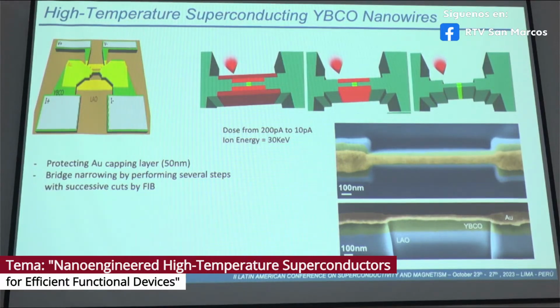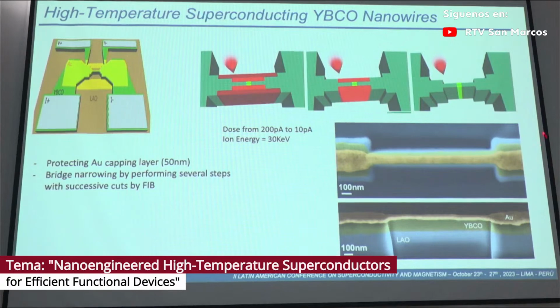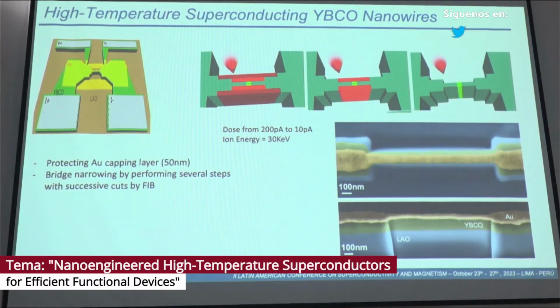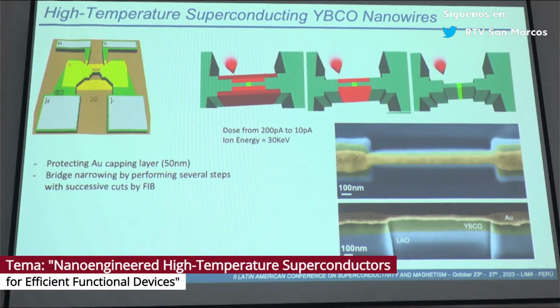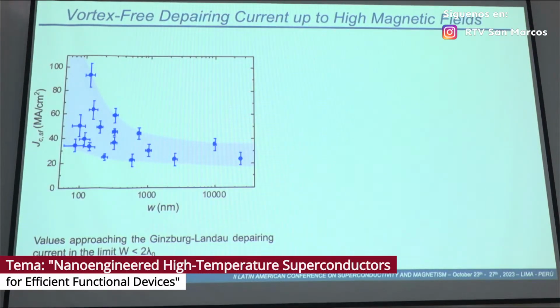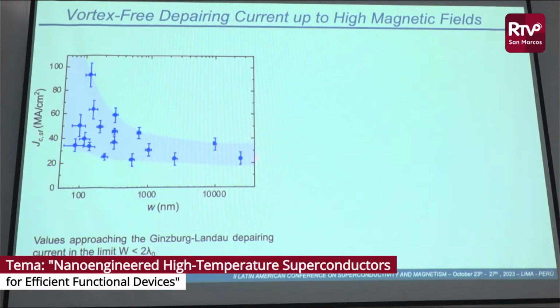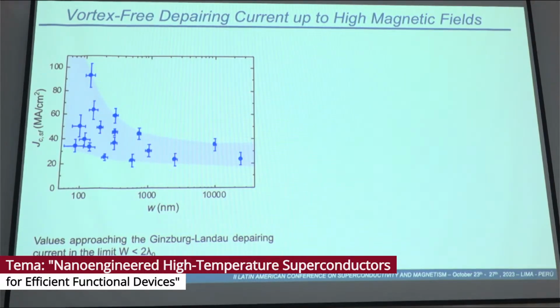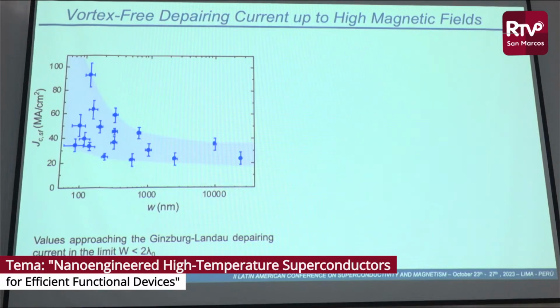We optimize the milling conditions in the system in order to fabricate these nanowires, which could be as narrow as 50 nanometers. And by exploring the properties of the nanowires, in this graph here I showed the JC as a function of the width of the nanowire, and we see that the critical current density can be enhanced up to very, very high fields by narrowing the nanowire, and we approach the depairing current in the system, which means that in this case, we have the maximum critical current density that the system can support without any losses for the vortex motion.